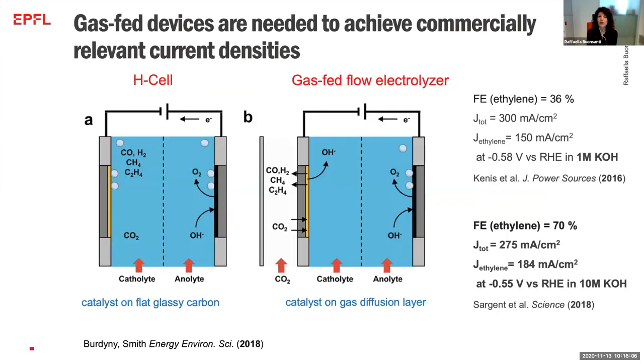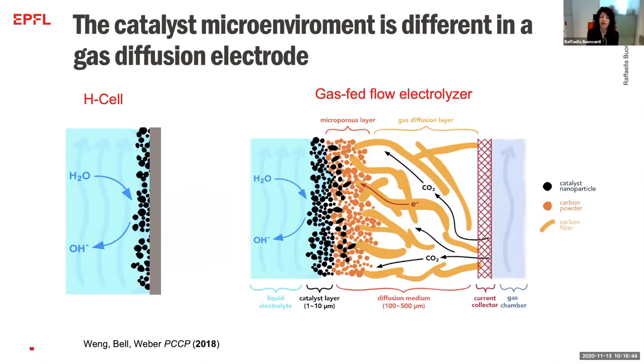Now, the results that I showed you so far were obtained in what we refer to as an H-cell. In this H-cell, the CO2 is dissolved in water, and because there is a solubility limit of CO2 in water, we are capped in the efficiency of the device. What has been shown in the literature to achieve commercially relevant current density is the use of a gas-fed electrolyzer, where the CO2 is supplied as a gas. This means quite a big change from a catalyst perspective, because in an H-cell the catalyst is just deposited on a flat glassy carbon.